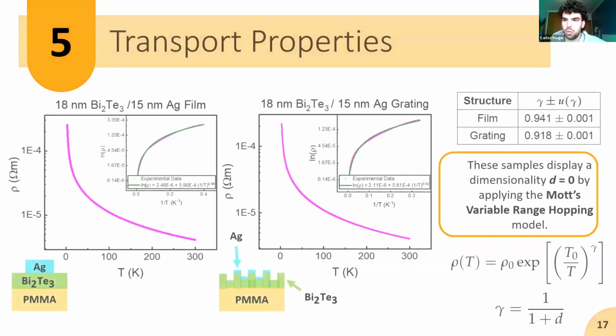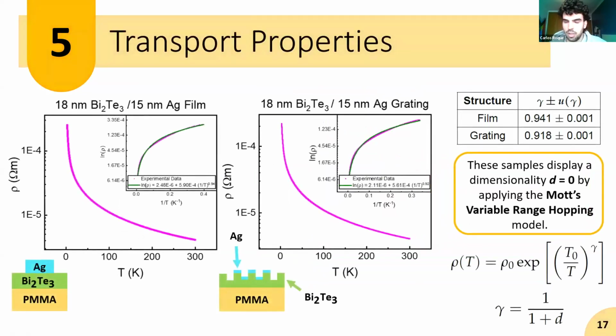Then we tried to measure the transport properties with no light shone on the sample. So we are not exciting plasmonic modes yet. We measured a film and a grating with bismuth tellurium and silver. The results are similar, so tailoring the sample does not affect the transport property, namely the resistivity dependence on temperature.